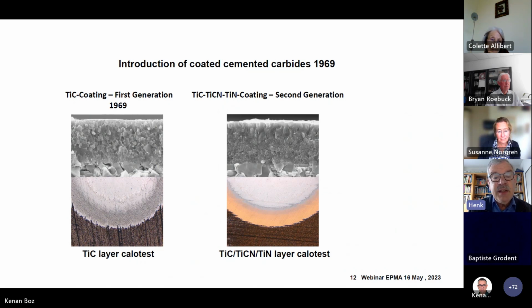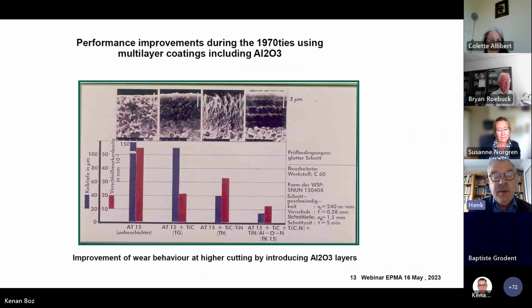And the next slide, please. The very broad introduction of aluminum oxide coatings was also a breakthrough, allowing much higher cutting speeds. It was very broadly introduced in those days by Sandvik, with a titanium carbide aluminum oxide coating, followed by multi-layer coatings.